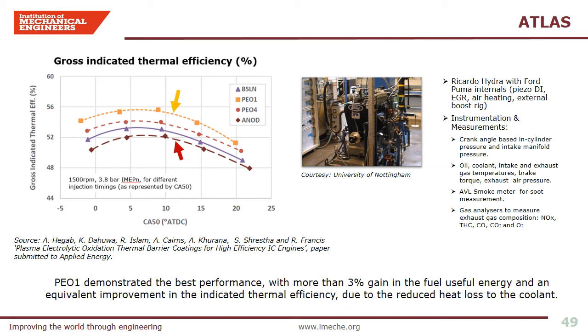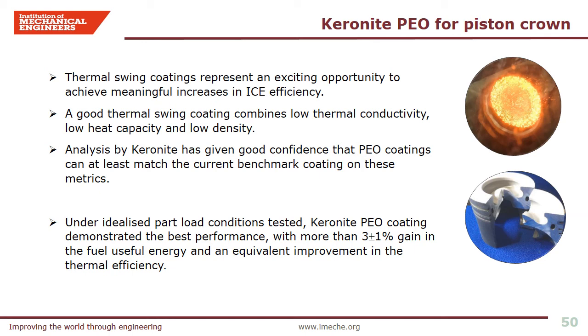A detailed work has been submitted for publication to the Journal of Applied Energy. In summary, thermal swing coatings represent an exciting opportunity to achieve meaningful increases in ICE efficiency. A good thermal swing coating combines low thermal conductivity, low heat capacity and low density. Analysis by Keronite and our partners has given good confidence that PEO coatings can at least match the current benchmark coating on these metrics. Under idealised part-load conditions tested, Keronite PEO coatings demonstrated the best performance with more than 3% gain in fuel useful energy and an equivalent improvement in thermal efficiency.